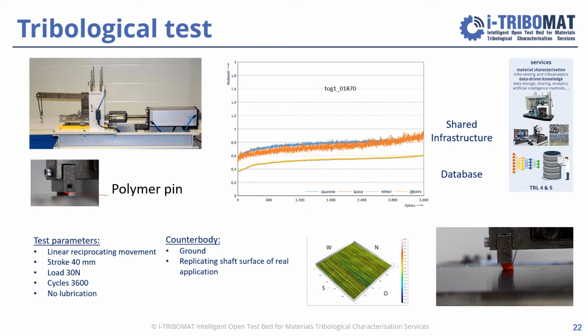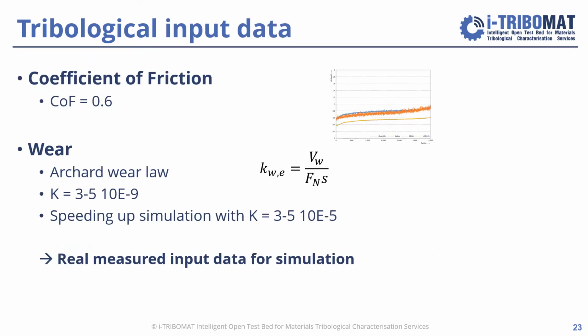A typical time series of an output can look like that. So we record an average coefficient of friction. We also record the peak values of each cycle. And you see this is much higher and is exposed to a certain scatter. But both is recorded and both is stored in the database to be reused also later on for further benchmarks to other materials or other testing conditions. So from this time series, we extract the coefficient of friction in the steady state region, which is here. And for the conditions of interest, we found that a coefficient of friction of 0.6 applies to this material. And this is what we're going to use later on in the simulation.